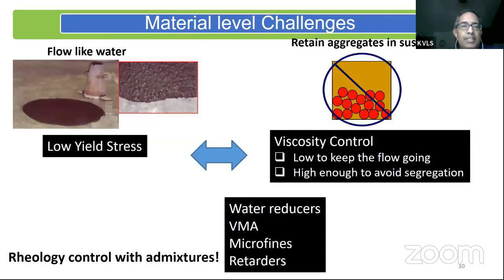So we use admixtures which lower a rheological property called the yield stress. We reduce the yield stress so that the material can flow, while we increase the viscosity of this particular concrete mixture, so that we do not get the aggregate segregating out or separating out, so that I'm able to get this homogeneous flow from concrete. And of course, this rheology control comes with the use of several admixtures. I have to use water reducers, viscosity modifying admixtures. We use a lot of microfines in the concrete. We also use some retarders.